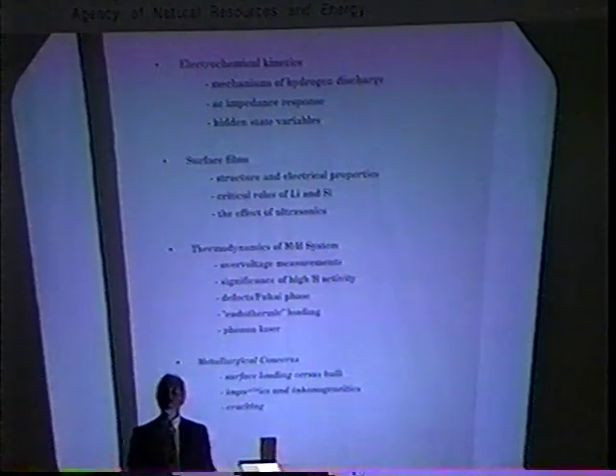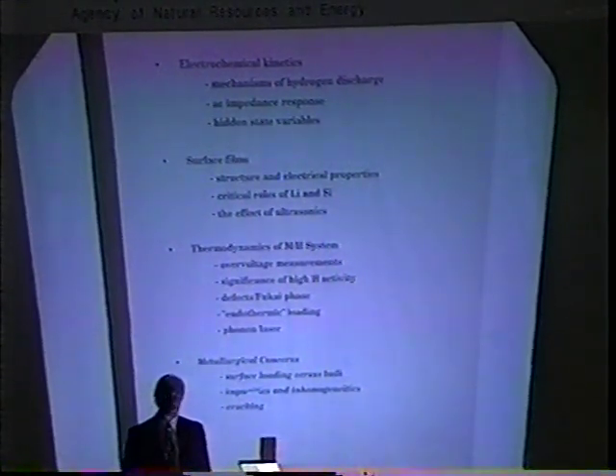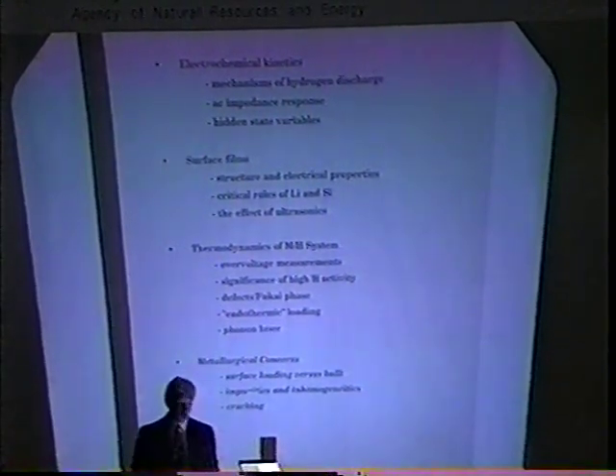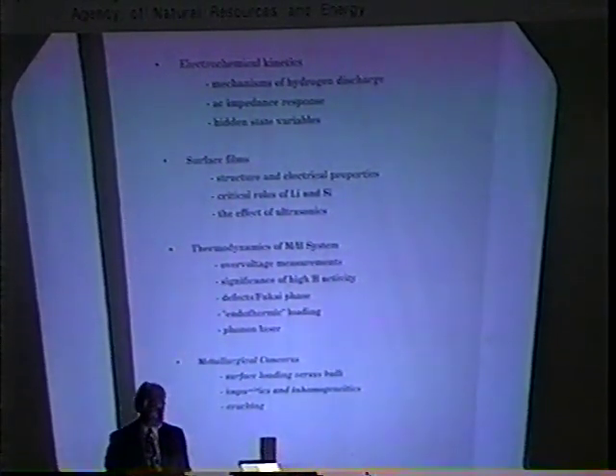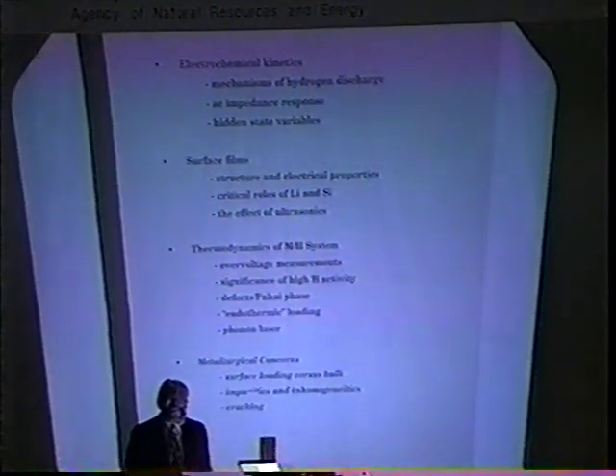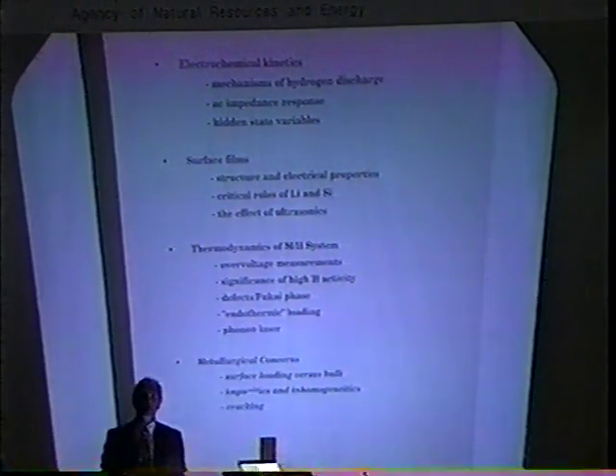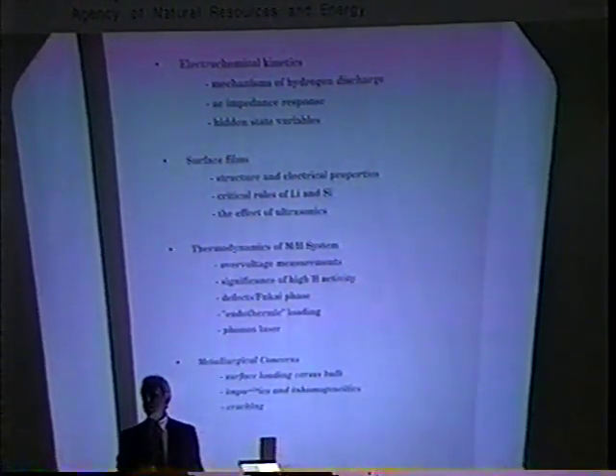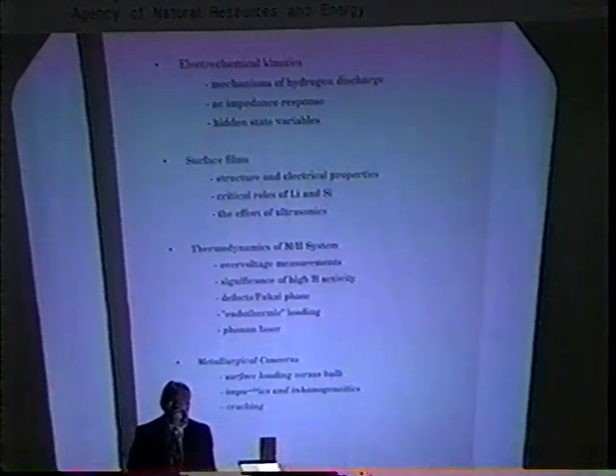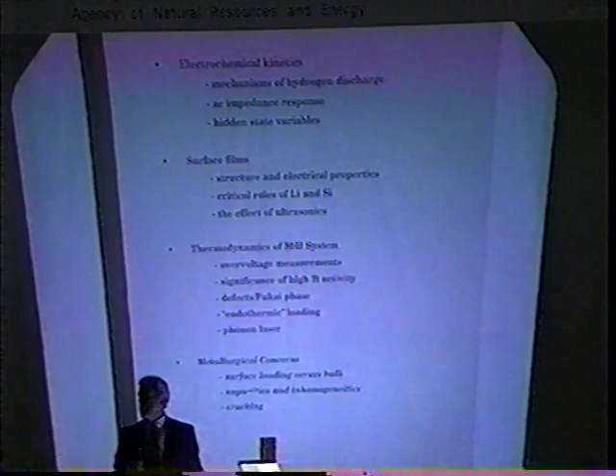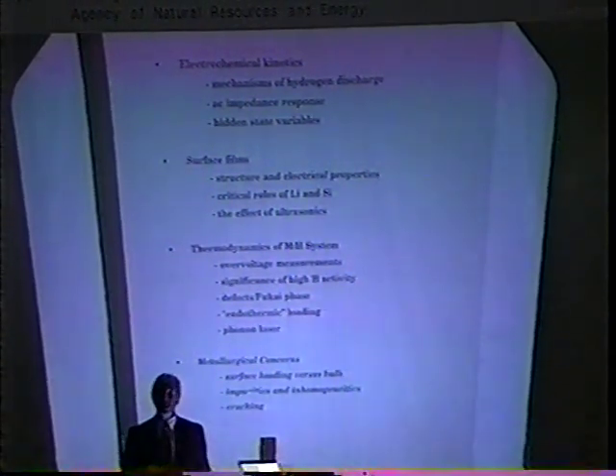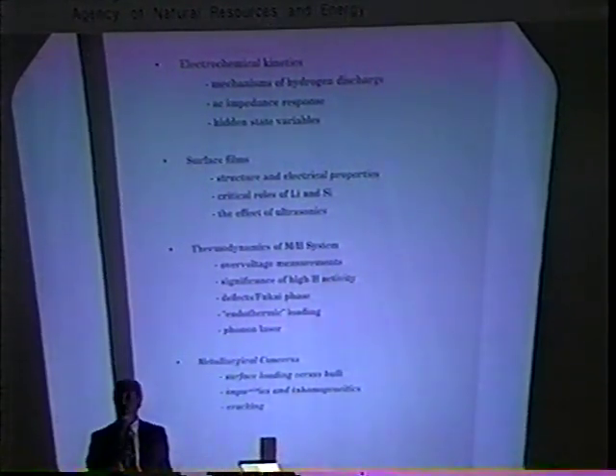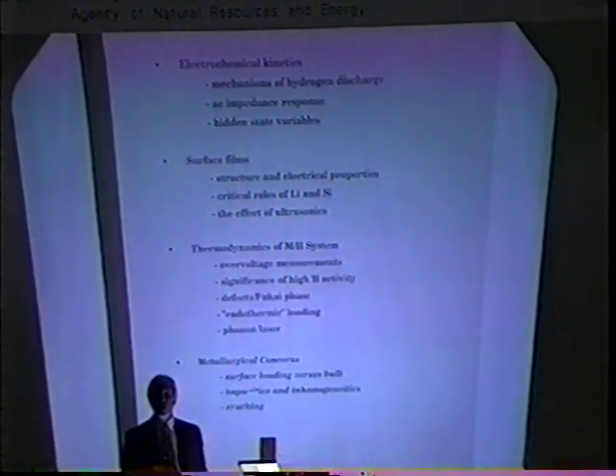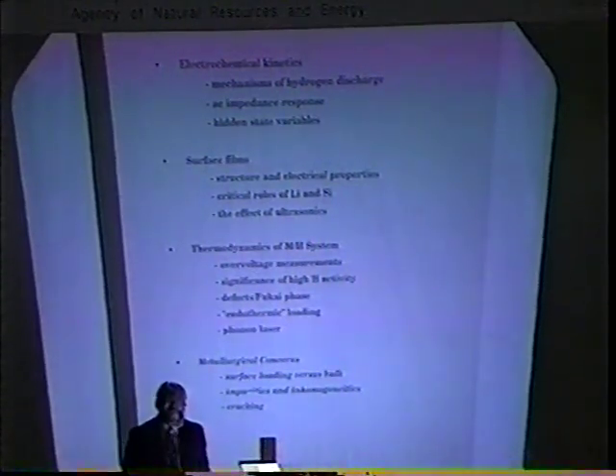Something that we've become much more interested in recently, not because I have any special interest in thermodynamics, but because it happens to be important: thermodynamics of metal hydrogen systems, making overvoltage measurements, the significance of high hydrogen activity. What does it mean to have an extremely high activity of hydrogen in the metal lattice? One of the things it does clearly, as Fukai has pointed out ably and in many publications, introduces a special defect character into the lattice. This may very well have important properties relating to cold fusion experiments, relating to other experiments, more fundamental issues.